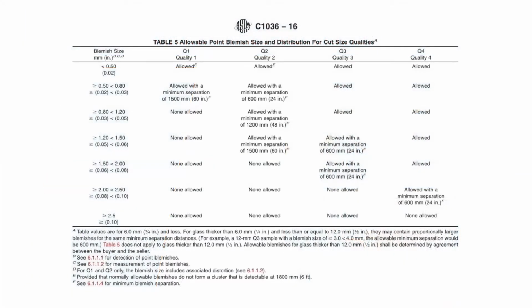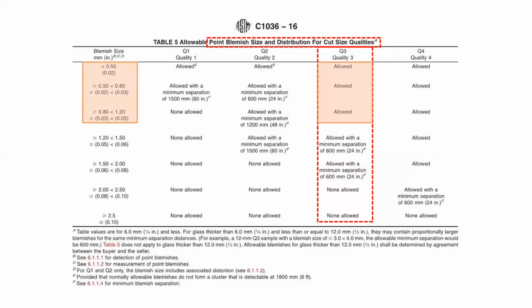Then we go into the standard itself. This is the table for point blemishes. Just about all the glass used on buildings is Q3 quality glass, architectural glass. And you can see that for point blemishes of a certain size in the orange highlighted area, they're just allowed in any number. But then further down in the criteria, you can see that some larger size blemishes are only allowed with a given spacing between them. And then if the blemishes get too large, they're just not allowed at all per the standard.